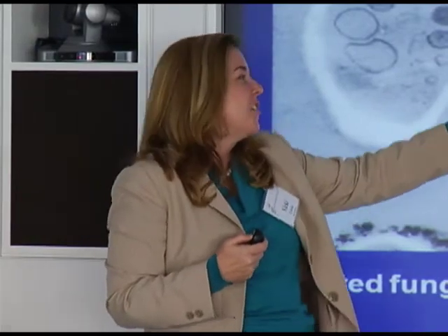But I want to focus on one of the key mechanisms because I think it is defining a little bit how our field is thinking about minimizing impact. So this is a picture of a bunch of human dermal fibroblasts in cell culture that have been treated with fullerenes. These materials were at very low concentrations, parts per billion in the solution, and they were soluble at that level. But over time, you start to see them associate with the surfaces of cells. And in the upper right corner is an AFM image. This is a case with fungi. Any organism you put them with, they go and they actually, these are large aggregates, but they interpenetrate the membranes. Because they're so hydrophobic, the concentration partitions into the most hydrophobic regions of organisms. And therein lies their effects.